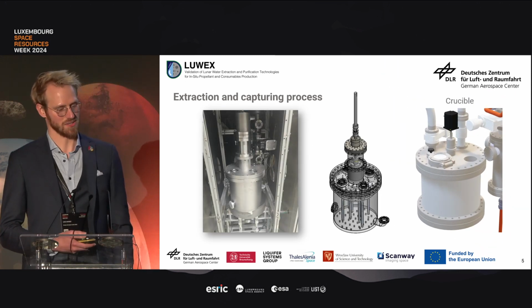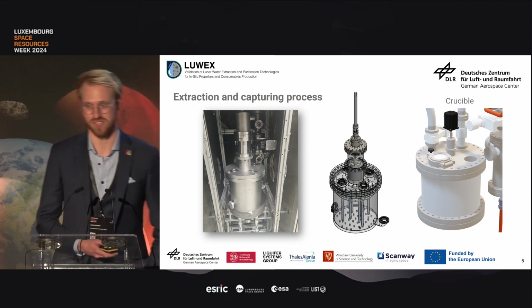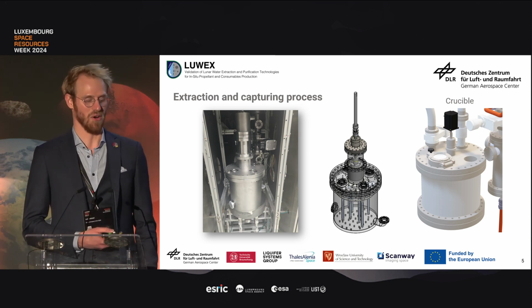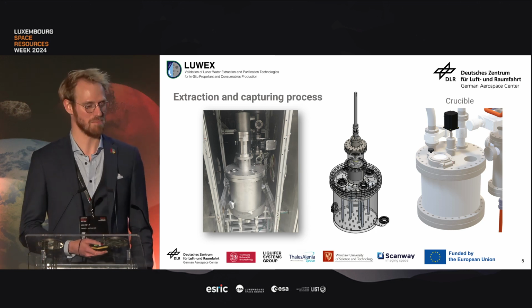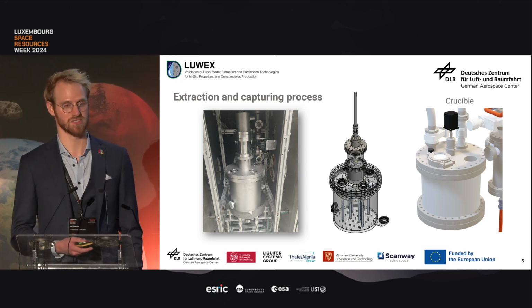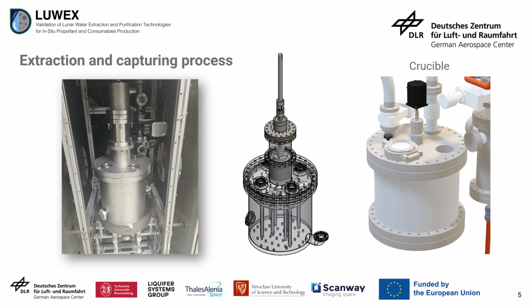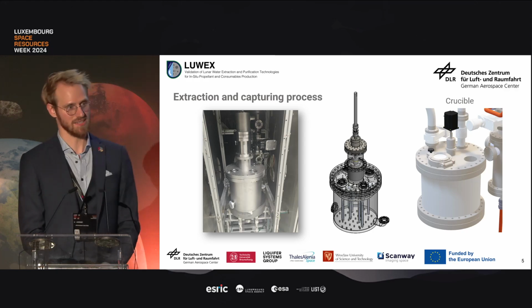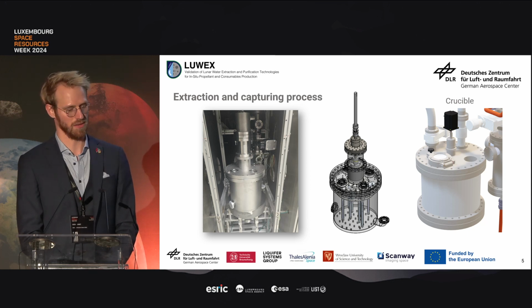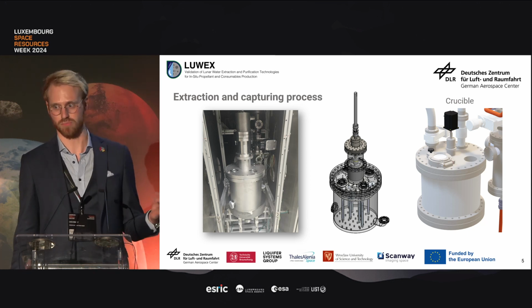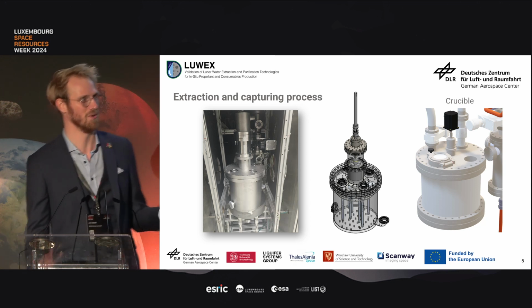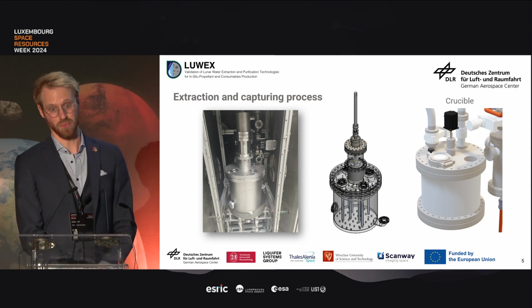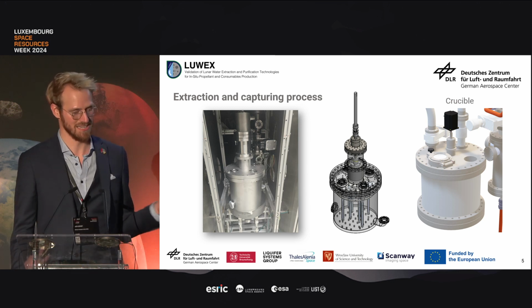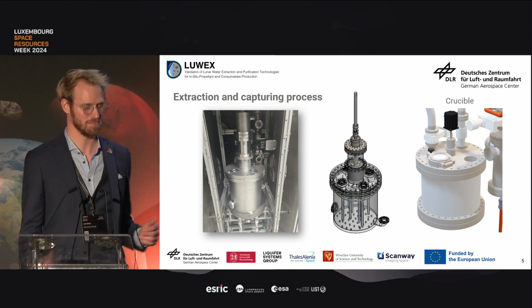On the picture on the right, you can see that we are currently integrating the whole system in Braunschweig. We hope that everything is done, let's say, mid-April, and then we have the first experiment results at the end of April. The 3D drawing in the middle is transparent, and there you can see 8 rods in the middle of the crucible. These are the rods that we will be heating and also stirring the icy regolith sample with to increase the effective thermal diffusivity, because as most of you probably know, the thermal conductivity of regolith is rather poor, so we want to do everything we can to get more heat into that sample and sublimate the ice.